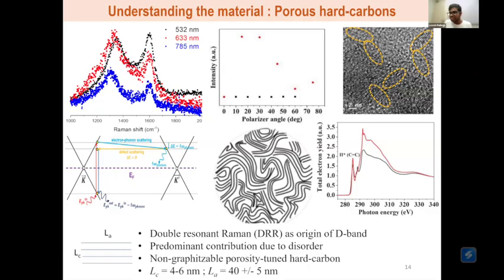Another question that we have is about the stability of these carbon structures at high temperature and in air. So I don't have the thermogravimetry, but this is basically because it resists graphitization. If you heat it in an inert atmosphere, the structure of the material doesn't degrade even at 2000 degrees centigrade. But when you heat it in oxygen or in an air kind of environment, the minute it starts going near 450 degrees, it's, at the end of the day, carbon. You can't change elemental carbon behavior. So it's going to react with the oxygen present in the ambience and form CO2. So it's stable till about 400 degrees centigrade, which is good enough for the applications that we are targeting.